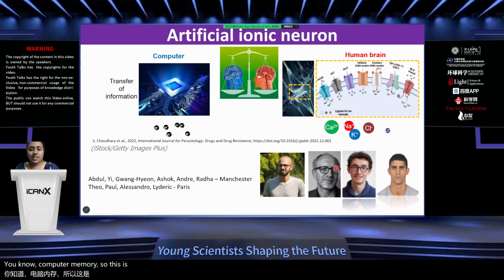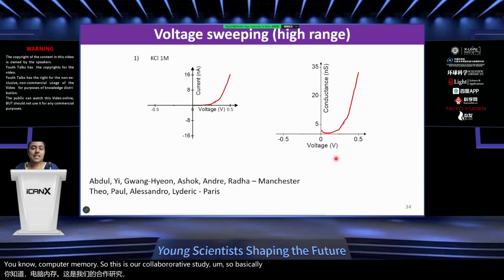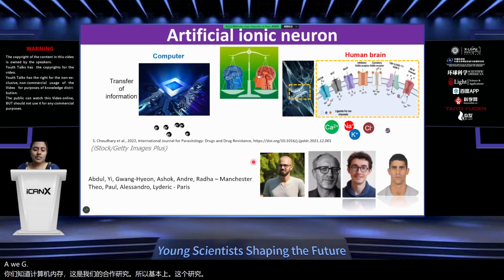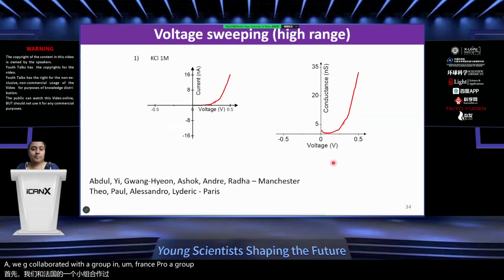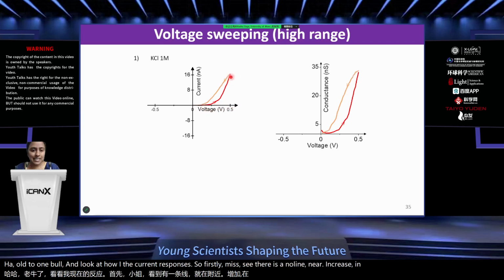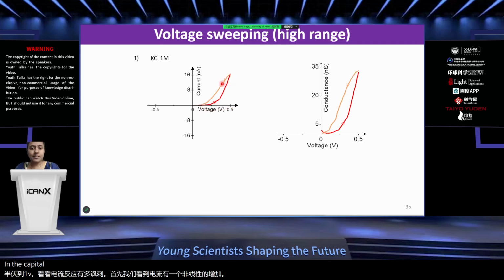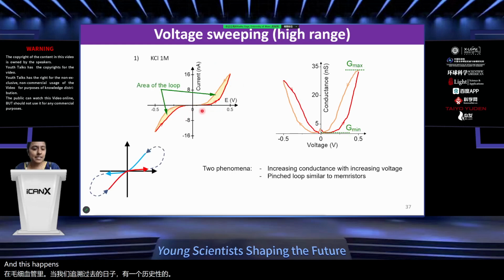So this is our collaborative study. Basically, in this study, we collaborated with a group in France, Professor Lideric's group. And what we studied here is looking at the ionic currents, but with much higher voltages. So we now go until like 0.5 volt to 1 volt and look at how the ionic current response is. Firstly, we see there is a nonlinear increase in the current in the capillaries, and when we trace the voltage back, there is a hysteresis, and this happens at both quadrants.